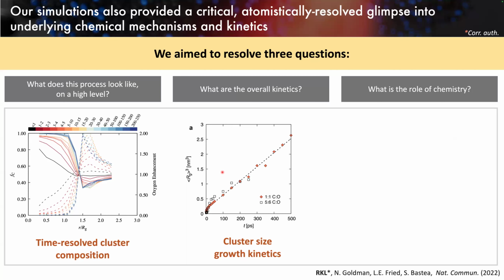So again, I mentioned that this linear regime is telling us that our clusters are maturing through an Ostwald ripening mechanism, which means our big clusters are growing due to our small clusters shrinking. That means we have to have a way of transporting carbon between those clusters.